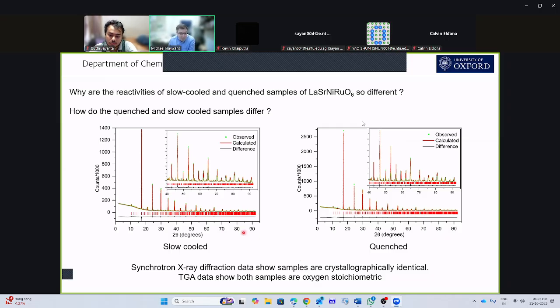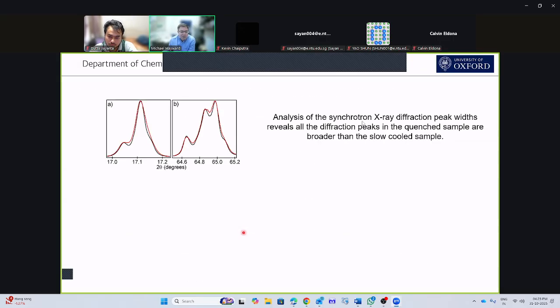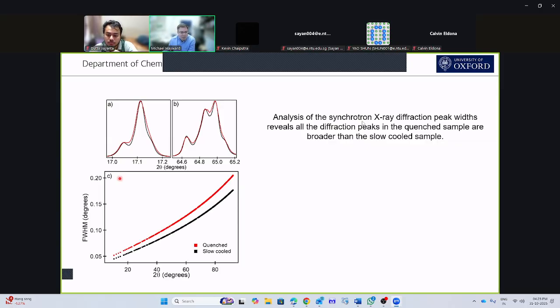They look principally identical. But if we look very carefully at the diffraction data, we can see that the diffraction peaks from the quenched sample, which I'm showing in red here, are very slightly broader than the slow cooled sample. And if we measure the width of the peaks as a function of the diffraction angle 2 theta, we can see clearly now that the quenched sample has broader diffraction peaks than the slow cooled sample.